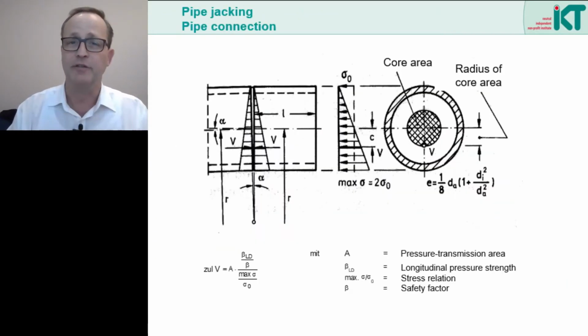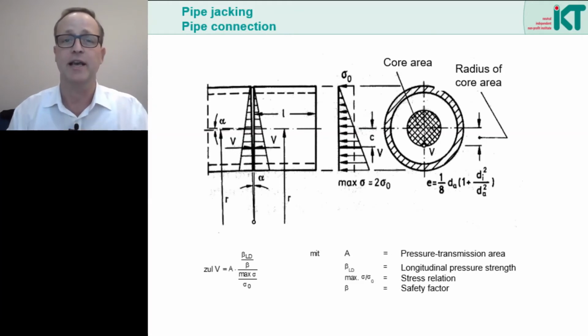An explanation for the high stresses at the edges can be found in the geometry of the pipe connection. The pipe ends lie parallel to each other. In the case of an angle joint, there is a linear distribution of strain in the pressure transmission ring. Depending on the material law, high strains then lead to more or less high stresses in the highly compressed area. If the material is plasticized, high stresses can be avoided.